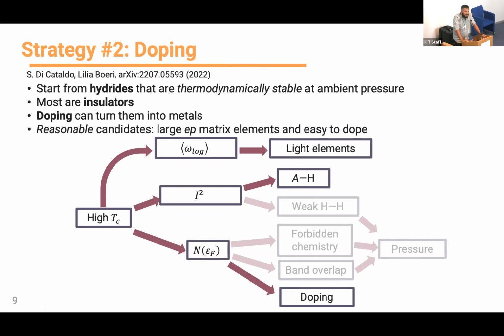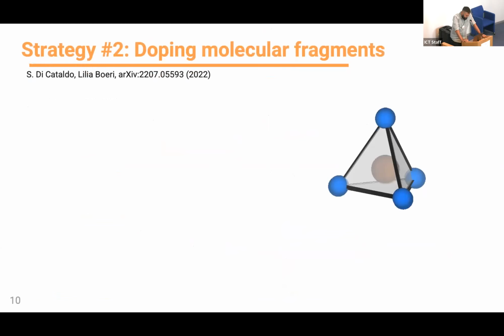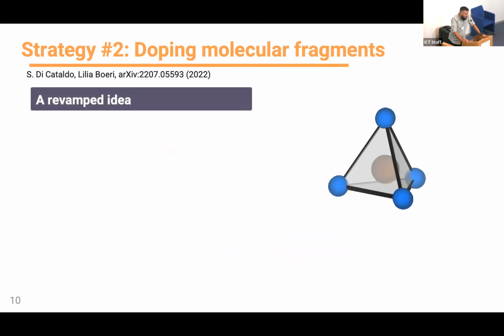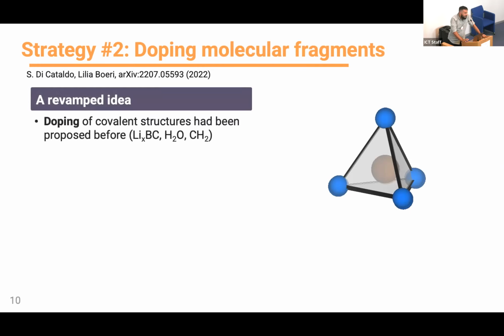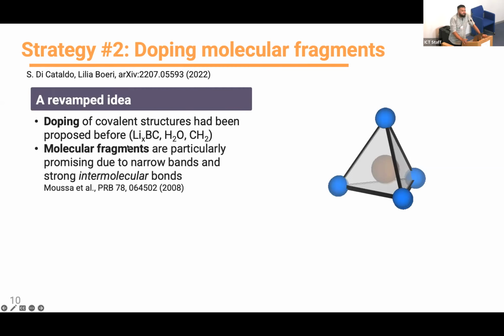And for reasonable candidates, I mean that they must have a large electron-phonon matrix element and they must be easy to dope. So in general, a very good playground where we think this might be possible is doping of molecular fragments. Now, as I said, this is not a completely new idea. It's more like a revamped idea because doping of covalent structures, like SiH4 or MgB2, has been proposed for several structures like lithium boron carbon, water, or polyethylene, but has essentially always failed. It was either predicted at extremely high pressure or it was never synthesized.